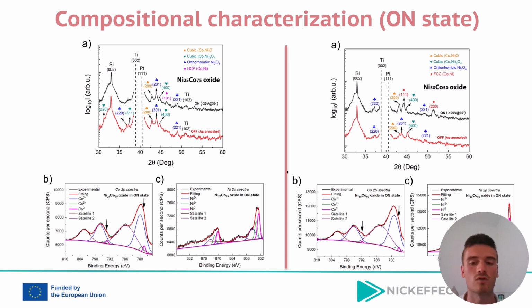Both phenomena confirm the transition from purely mixed nickel and cobalt oxide to a combination of oxide plus metallic phases in the on state. We can say that this discovery confirms and somehow provides a true explanation of how effective the electrochemical reduction was after the samples were gated, which was responsible for explaining the observed increase in magnetization.